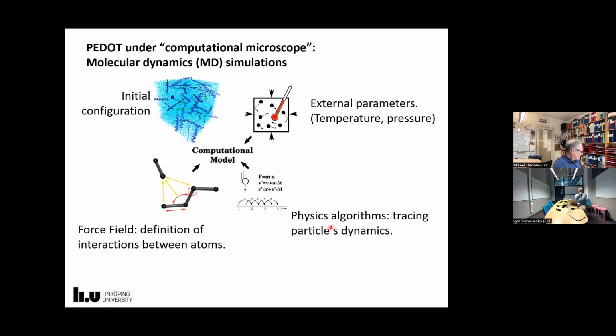Okay, now, of course, experimentally, we cannot see what happens inside the PEDOT, but we can do it using a so-called computational microscope. This means that we can do molecular dynamics simulations to see what happens there. And to give you some ideas of what you do in molecular dynamics simulations, you start with the initial system. So, for example, you put a lot of separate PEDOT chains. You define your temperature, pressure, then you define how atoms interact, and then you start basically performing physical algorithms like tracing particle dynamics.